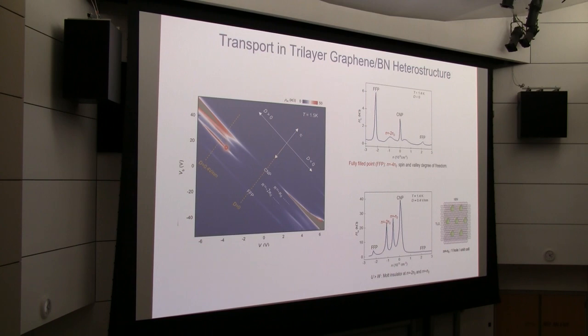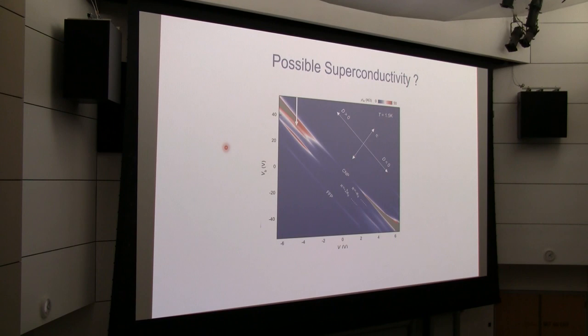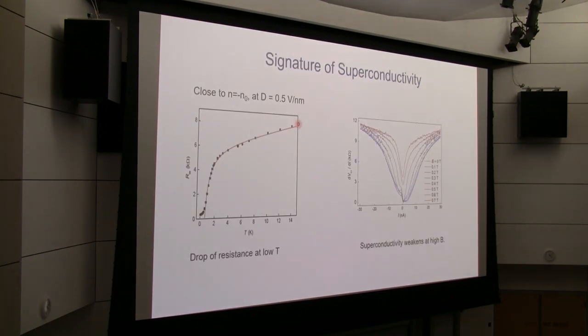So a question then to be asked is, if you have a Mott insulator, is it possible to dope it and realize superconductivity? To answer that question, we collaborated with Professor Gordon here. We searched the phase diagram, and we found that doped Mott insulators don't always give you superconductivity. So we need to look carefully, and in a relatively narrow range pointed out here, we actually see signatures of superconductivity, where the resistance drops more than an order of magnitude at low temperature, and it also shows critical behavior where the resistance becomes higher at large current. Also, it gets suppressed by both in-plane and vertical magnetic field.